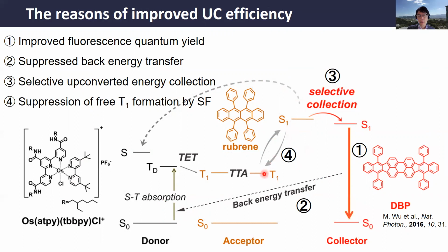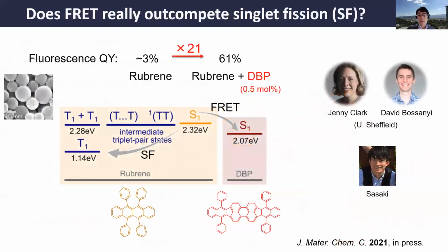the rubrene singlet energy level is about two times that of the triplet. So not only TTA, but also singlet fission can happen. People have assumed that this singlet energy collection can outcompete this singlet fission, but by collaborating with Jenny and David in Sheffield, we found it's actually not the case.